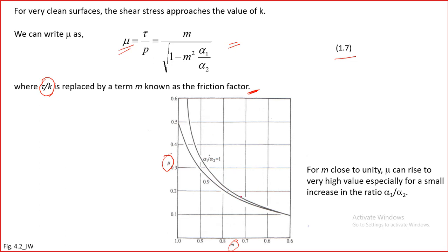Using this equation, if you plot, you will find that when M is close to unity, close to 1, mu rises very sharply for whatever alpha 1 over alpha 2. So whatever value you take, the coefficient of friction will be large when M is close to 1. And for alpha 1 over alpha 2 close to 1, the coefficient of friction is even larger, very, very high. This has also been found by experimental evidence. What it says is that M, which is tau over K, should not be close to unity. So if this ratio is close to 1, coefficient of friction will automatically be high.